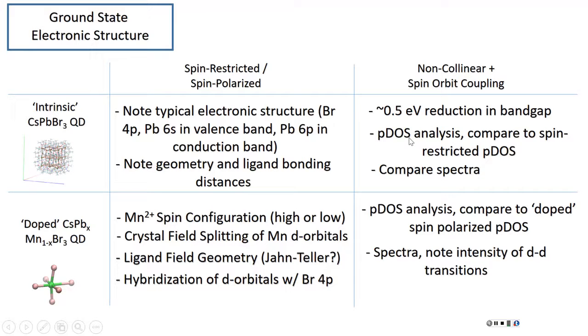Which use spin orbit coupling. And it reduced the band gap by about 0.5 eV, which has been reported by other people. And then I was going to do a PDOS analysis because of spin orbit coupling. The best way I can think of is mixing of states, because that's what spin orbit does.